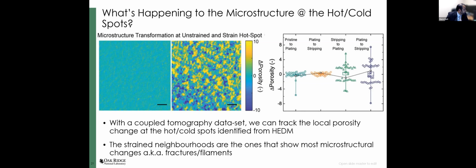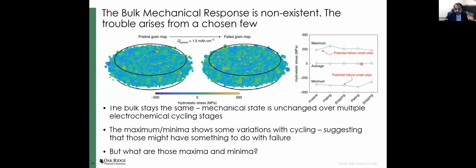Reeju asked, the average hydrostatic stress strain was shown as 0, so how did we calculate the D0 for the different phases? That's a good question. The D0 was chosen from the lattice parameter fitting from the diffraction profiles we got. We fit the diffraction patterns obtained from these materials to identify a lattice spacing for these cubic materials, and we used that as the D0 for these phases, and that's why we have this average stress at 0.